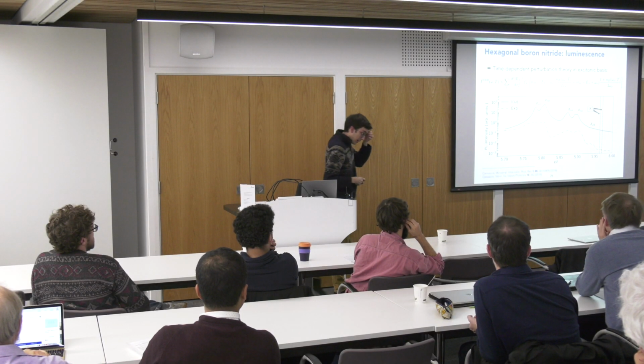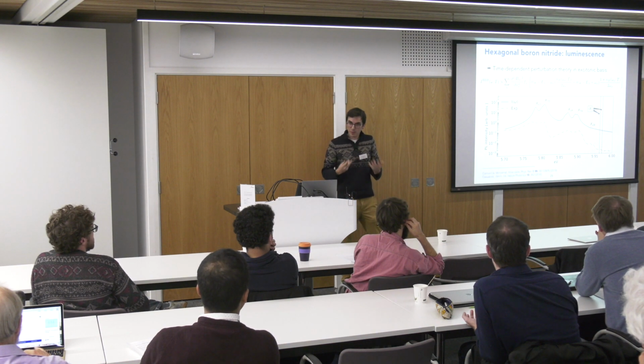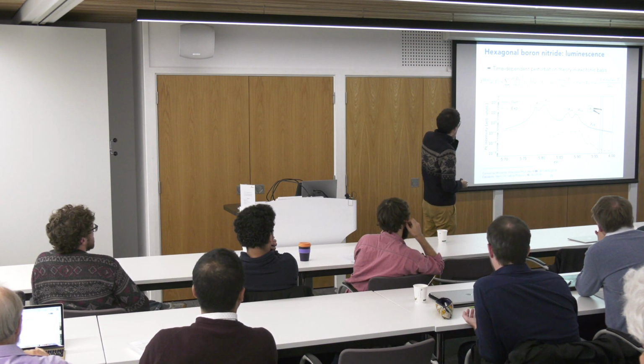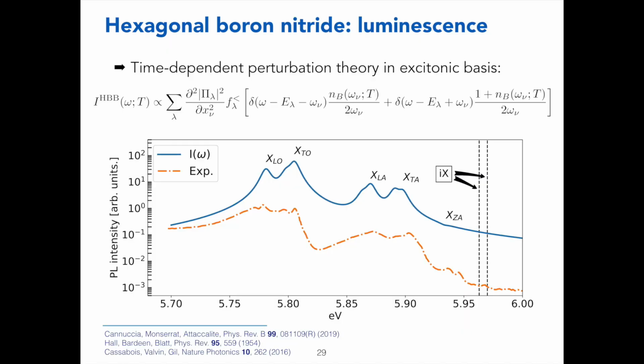So what we did then is we did one of the very first ever calculations of exciton-phonon coupling purely from first principles. And what we had to do actually was we had to extend the ideas of this Bethe-Salpeter equation that I've explained earlier, which is usually used for absorption processes, to recombination processes to study luminescence, and that's something called the out-of-equilibrium Bethe-Salpeter equation. And if you just do those calculations, you get the exciton lines here, but you don't see any signal because it's an indirect bandgap material and you don't get any luminescence. What we then did was we used perturbation theory in this case to make the calculations feasible, to calculate the change in the matrix elements due to having phonons in your system. And then these are just conservation of energy rules and phonon occupation factors.